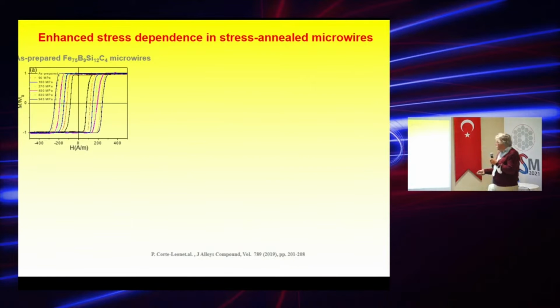Okay. So another important issue: for sensors, for magnetoelastic sensors, it's important to know the stress dependence of magnetic properties. Here are the as-prepared iron-rich samples which we employed for these studies, and we applied stress during the measurements. So this is without stress, and on the application of stress, an increase of coercivity was observed, but the shape of the hysteresis loop was different.